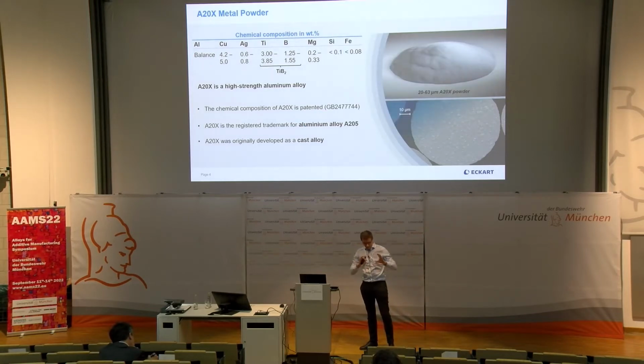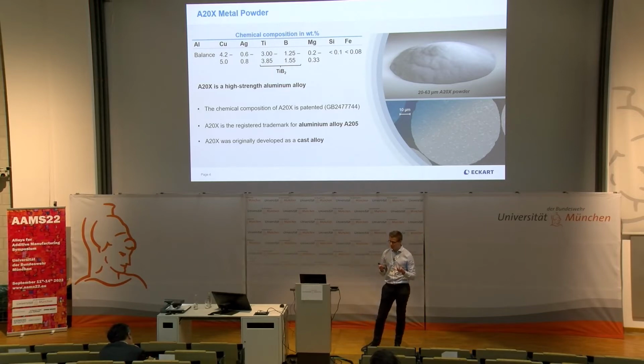So the casting part of the business is still ongoing, but what I found interesting is that the problem that A20X solved back then was very similar to the problems that we are tackling now, which is the formation of major metallurgical defects during the process. We have seen it a few times, the main one being solidification cracks or hot cracks, and A20X solved that by grain refinement. As it turns out, this alloy is also very well, if not better, suited for additive manufacturing.